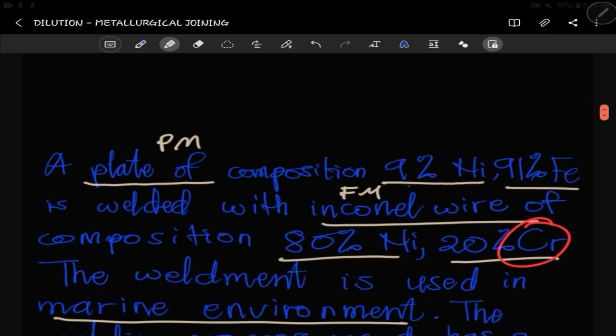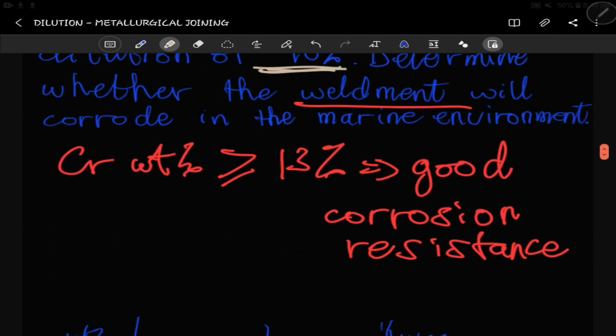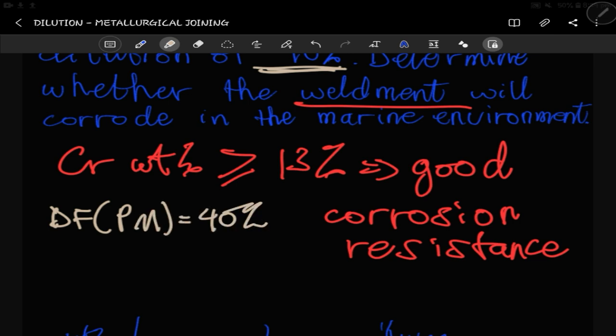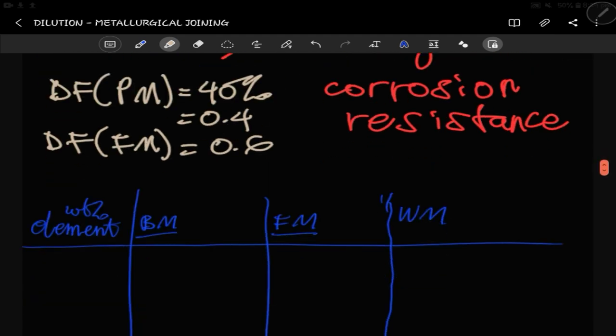So the 40% is basically for the parent metal. That's the dilution factor. The dilution factor for the parent metal is 40%, right? This 40% is basically 0.4. This will mean that the dilution factor for the filler metal will be 100 minus the 40%. So that gives us 60%, which is basically 0.6, right? And this is what we will use.